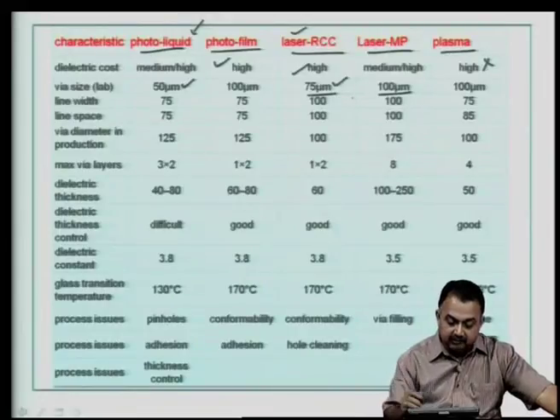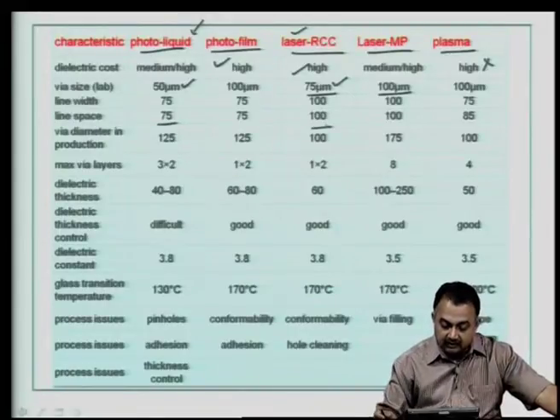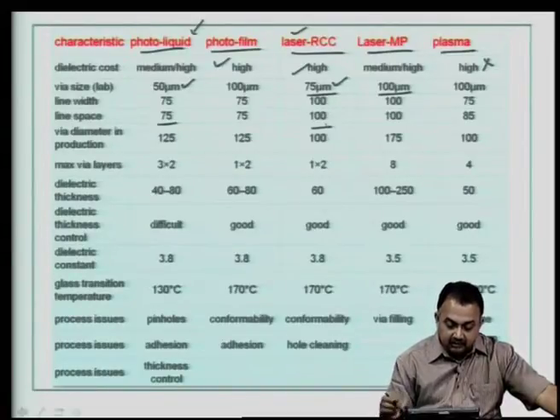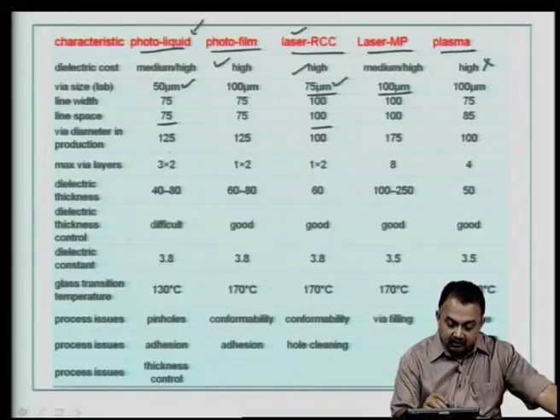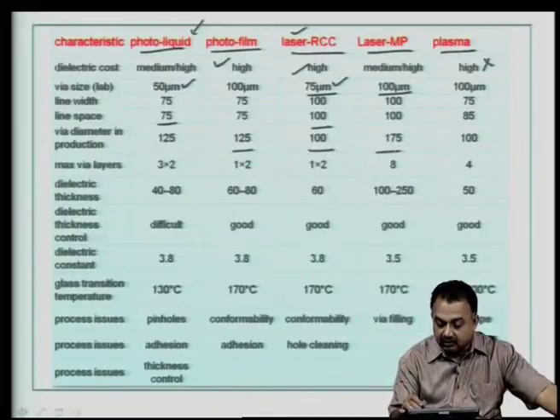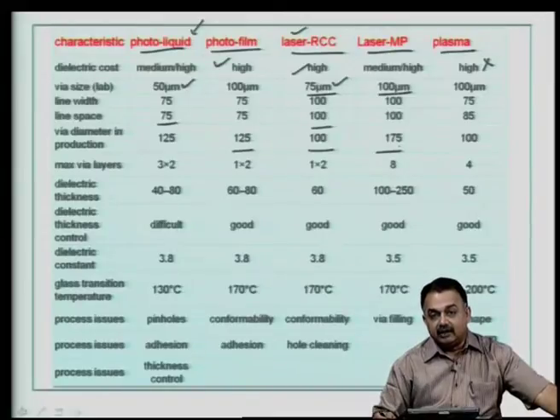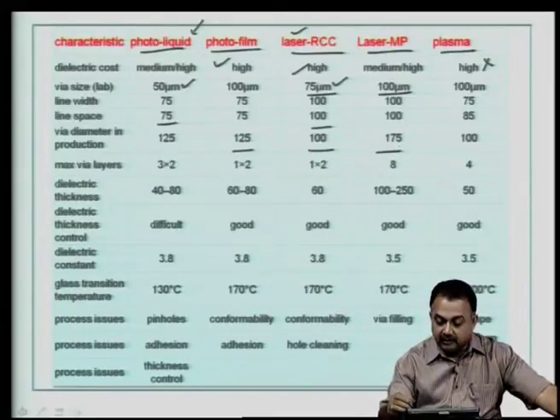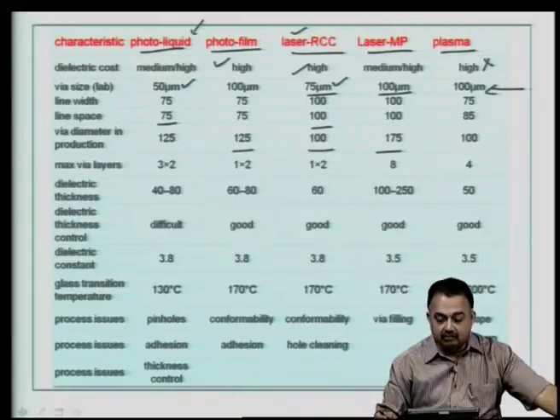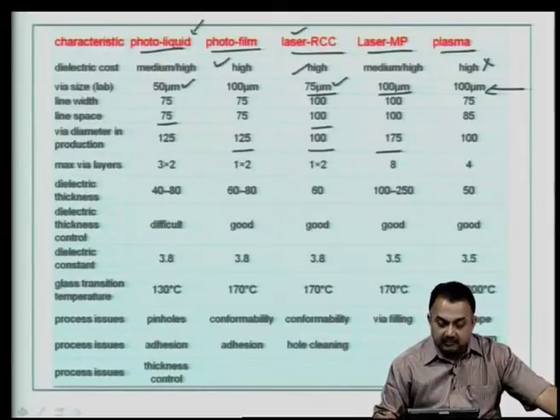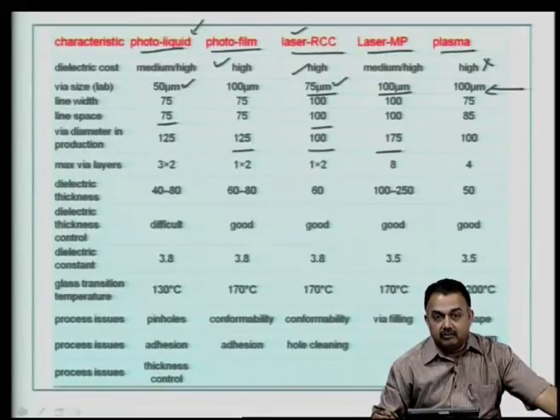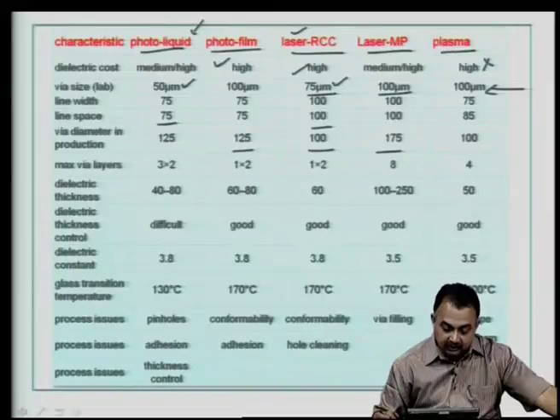The line width and spacing typically 75 to 100 microns for all these processes. Then you have the via diameter in production is currently about 100 to 125, in some cases even more, 150 microns or so that the high reliability is maintained, whereas for prototyping one can go for these kind of numbers. The via layers maximum is 4 additional layers, but in some cases people have gone in for 6 layers. So, typically if you start with a 4 layer board, you can build 2 to 3 additional layers.